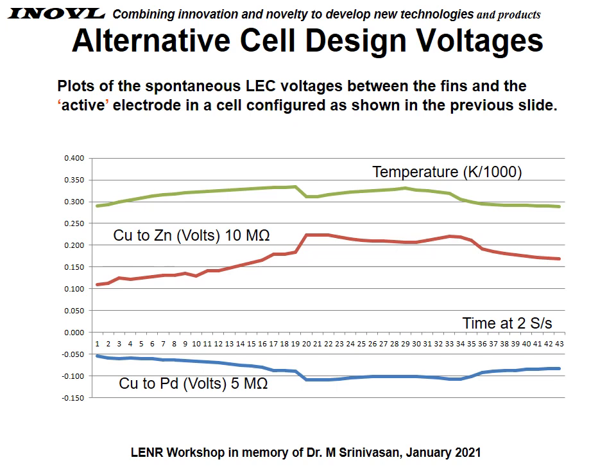The temperature is Kelvin divided by 1,000, and so you see as the temperature goes up a little bit, the copper to zinc volts through a 10 megohm load ranges from about 100 millivolts to 225 millivolts. At the same time, the copper to Pd voltage through a 5 megohm load was negative, starting at about minus 50 millivolts down to a little over minus 100 millivolts. And so this slide shows that it is possible to harvest some of this energy, which is the contact potential difference or Volta effect.